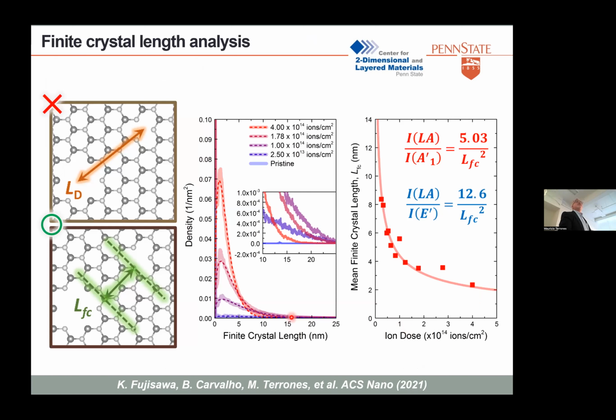One of the things that we did: other papers have used, for graphene, the defect to defect distance, but that doesn't work when you have too many defects or when the defects coalesce, right? Because then you have a larger hole, and it will not give you the right defect to defect distance. So what we did is use the finite crystal length. We define this, and then with different ions we define the finite crystal length. We measure this experimentally and then we plot it here, right?